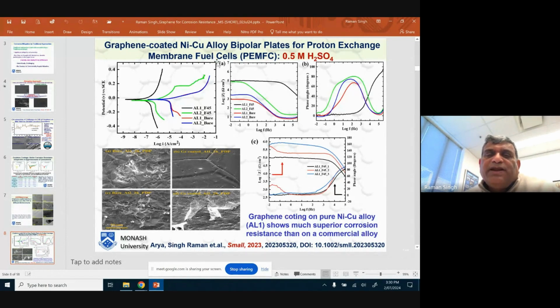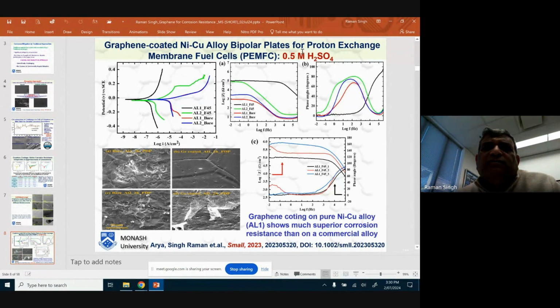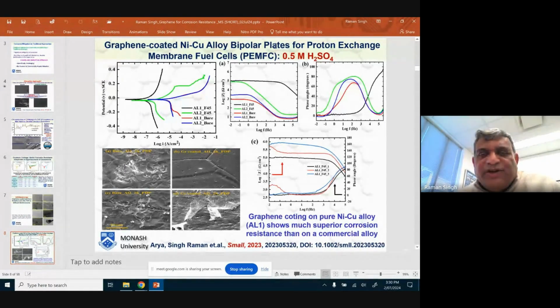The bipolar plates have this requirement of having good corrosion resistance, because even if you chose a highly corrosion resistant alloy like stainless steel or titanium alloy, it develops a corrosion product film, that is oxide or hydroxide. It develops on the surface, and that film is at the best semiconducting or non-conducting, whereas you would need this component to be conducting. So with period of time, because of formation of corrosion product, the conductivity is lost, and that's where there's huge problem.